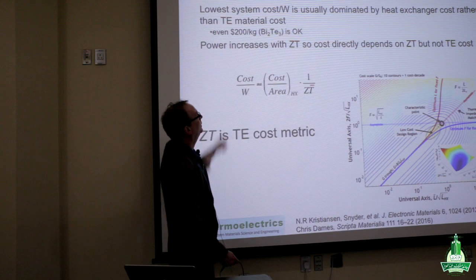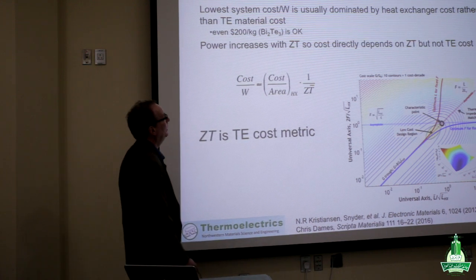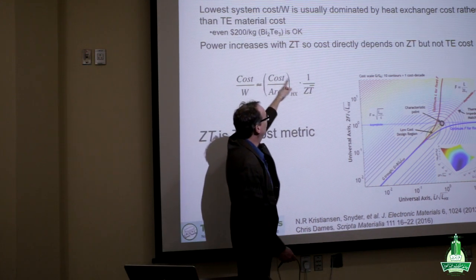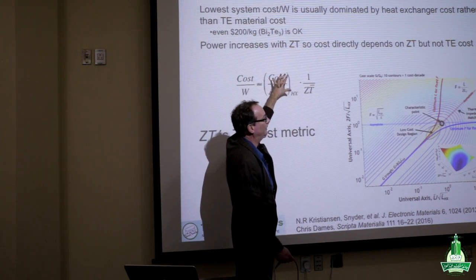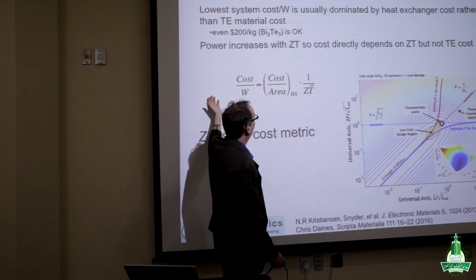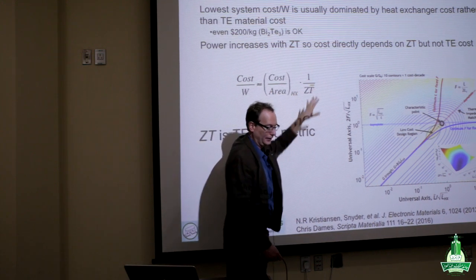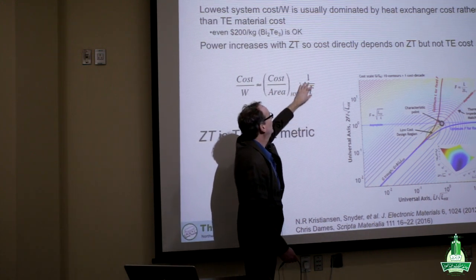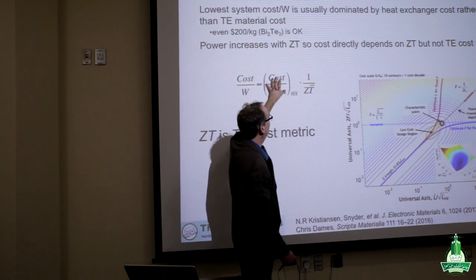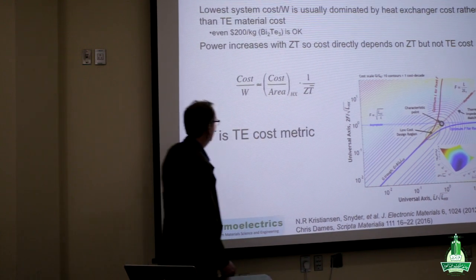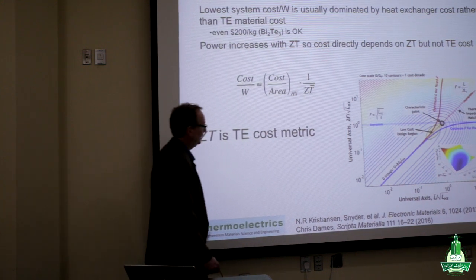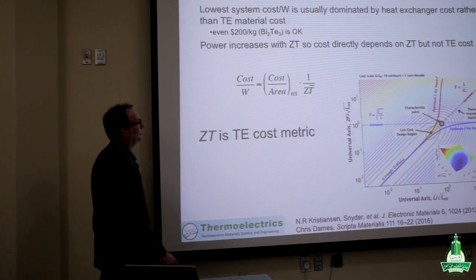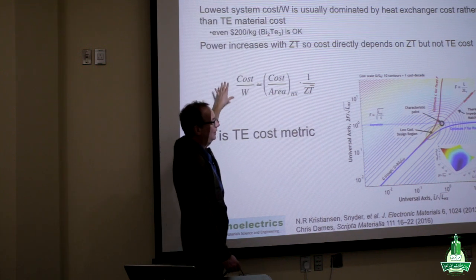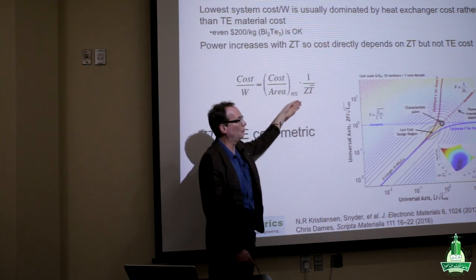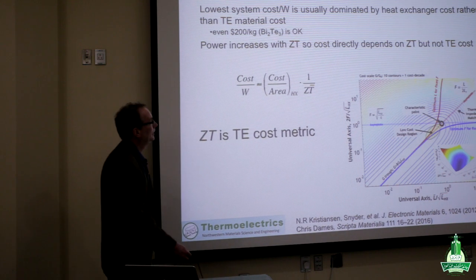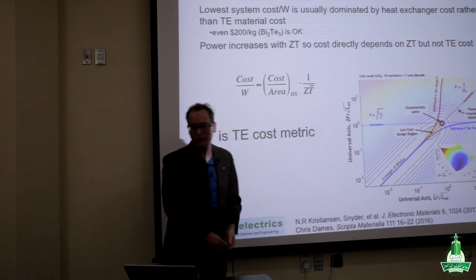So even at $200 a kilogram for bismuth telluride, the dominant cost of the system is that heat exchanger. And then in order to get the power out of that system, the average device ZT is what matters. And so the cost per watt is essentially the heat exchanger cost and the ZT. So again, the ZT is the cost metric. So if you're going to design a system for cost, I still say work with your highest ZT materials. But work on those heat exchangers.